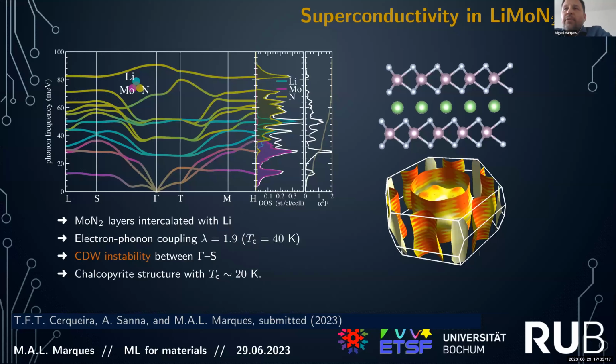Well, we performed the electron phonon calculation. We used Eliashberg theory. We used density functional theory for superconductors. And our lowest estimate for the transition temperature is 40 Kelvin, which, if it's confirmed, would actually be a record for conventional superconductivity. Now, this is again in the computer.